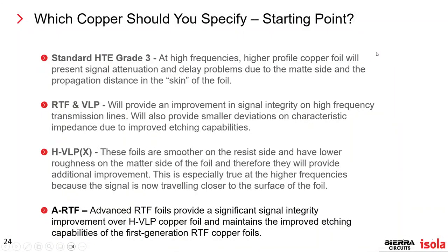As for which foils to use as a starting point: HTE standard Grade 3 is used for standard products where they're low cost and doing standard FR4 — foil losses are relatively small. RTF and VLP benefits are more about etching capabilities and some better high-frequency performance, though from a loss perspective they are still fairly high loss conductor foils. HVLP has been the standard for about 5 to 6 years for high-end ultra-low-loss and very low loss materials — Isola's I-Tera MT40 and Tachyon 100G are examples. As dielectric losses are reduced, conductor losses can only be reduced by developments in the copper foil.